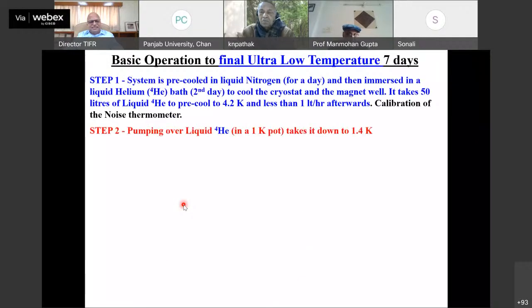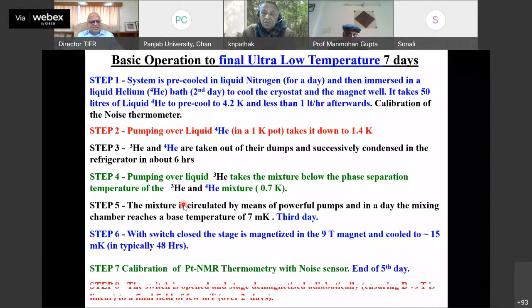So I think the basic operation is not for the faint-hearted, as Grover mentioned, that these are very difficult experiments. You start with liquid nitrogen cooling, then you start the helium-3, helium-4 dilution refrigerator, calibration of the thermometers. It is done every run, okay? And after 7 days, if there is no power fluctuations, you will reach about 50 microkelvin.